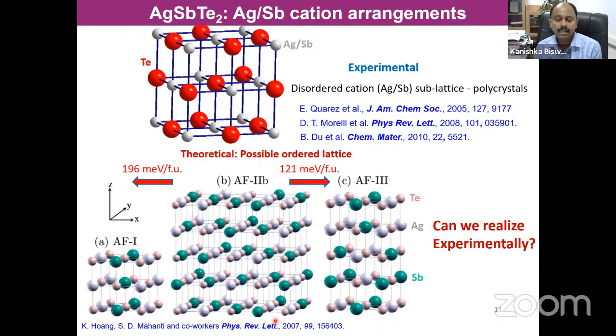They said that several ordered structures are possible if silver and antimony order in the sodium position. Then it creates a supercell, and it will not have exactly the sodium chloride structure, but it can have a cubic or tetragonal type of structure where silver and antimony are ordered. Okay, and we have tried to make this ordered structure since 2012-13, but we have not succeeded for many years. And you can ask me why we are looking for this ordered structure, right?